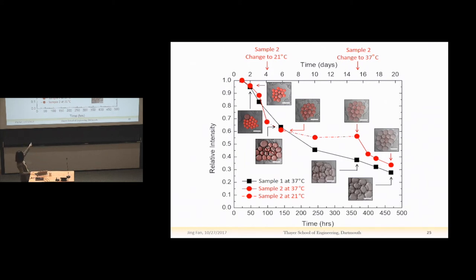And it clearly shows that the colloidosome will release their cargo faster at higher temperature. And we should note that how good this thermal responsive release behavior is depends on the size of the nanoparticles and the block copolymer molecules. We should use block copolymer molecules with a size comparable to the interstitial pore size on the shell. And it also depends on the molecular size of the target, the active materials encapsulated inside. Okay.